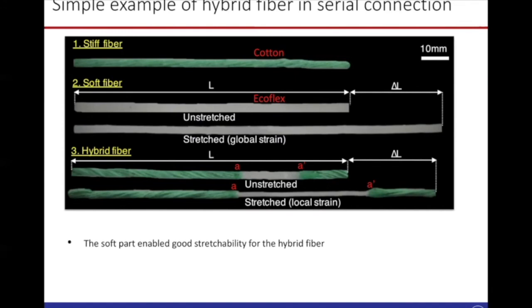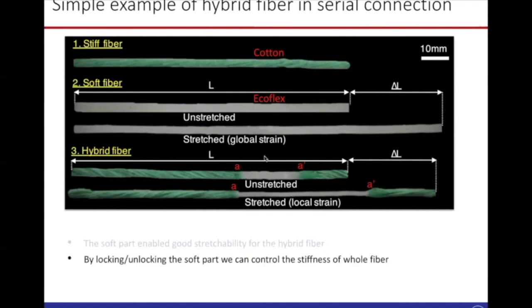Now it's interesting, since the volume fraction is small for the soft part, by locking or unlocking the soft part, I can control the stiffness of the hybrid fiber, because the stiffness of the hybrid fiber now depends on the stiffness of the soft part. When it's locked, it becomes highly stiff. When it gets unlocked, it becomes highly soft.